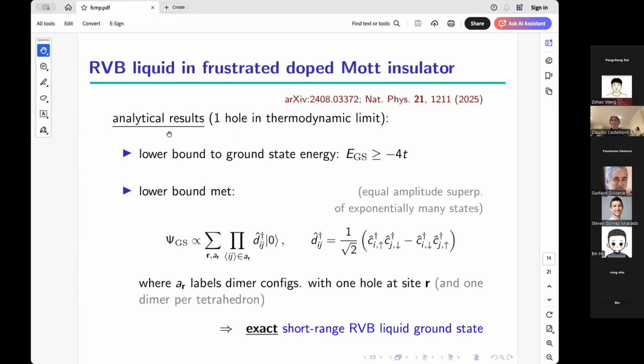Interestingly, this is an exact analytical result where we can prove with paper and pen, with one hole in the thermodynamic limit. The proof actually spans two parts. One is you can prove the ground state is lower bounded by minus 4t, and then the lower bound is met by this superposition that formally is written here: the sum over all hole positions, sum over all possible singlet arrangements, of which there are exponentially many, of the product of the singlet creation operators over all of these nearest neighbor pairs acting on the vacuum, right? If you want to see it formally, or hopefully what I said hand-wavingly was clear enough.